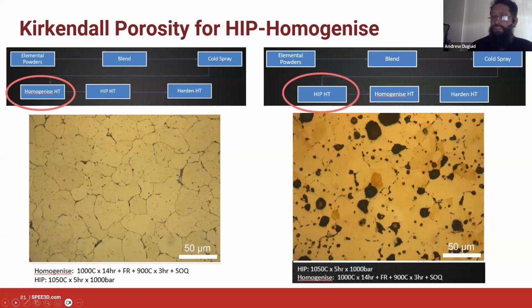And what that means is that the homogenization step is still homogenizing the alloy after it's otherwise been formed. And the problem with that is that the aluminium is gradually diffusing away into the matrix. There's no longer the potential to generate any liquid phase. Instead, what you wind up with is these voids where the aluminium-rich areas used to be, and there's nothing in that sequence that's going to do anything about those voids. And so, obviously, we conclude from that the sequence on the left is the one that we want to proceed with, and that's what we did. So if we can go on to the next slide.